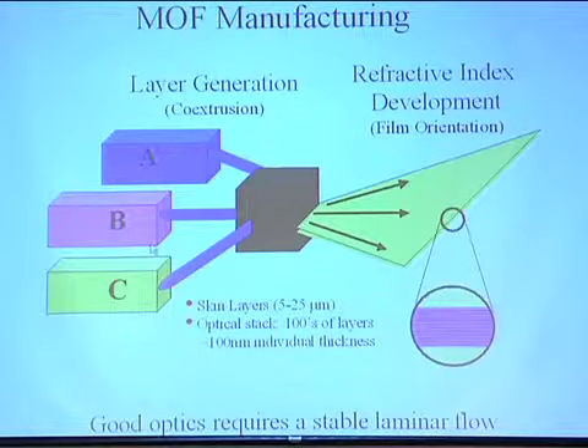Here's another cartoon showing how we make these films. We have these film lines with extruders, which basically melt polymer pellets and bring them together in a manifold like a car engine, except instead of eight manifolds, we have 100 to 300 manifolds. And they alternate the layers, and it comes out of a die like this and is quenched on a casting wheel, and then the film is stretched. And by stretching it, you make the layers thinner, get them down to nanometers thick, and you make them birefringent, which gives them a very high optical power.